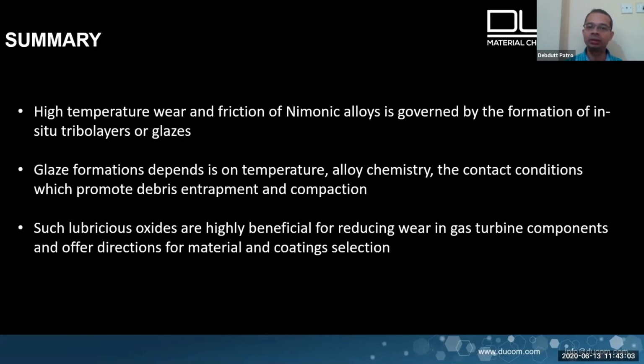So quick summary of this test. So at high temperatures, some of these nickel alloys which are proposed to be used, they show low friction, low wear, and this is because of the in situ formation of these tribo layers, third bodies, or glazes. These oxides are highly beneficial in gas turbine components, and they also help us discover new materials, identify new coatings which we can apply to reduce friction and wear even further, all from setting up a simple experiment in the lab.